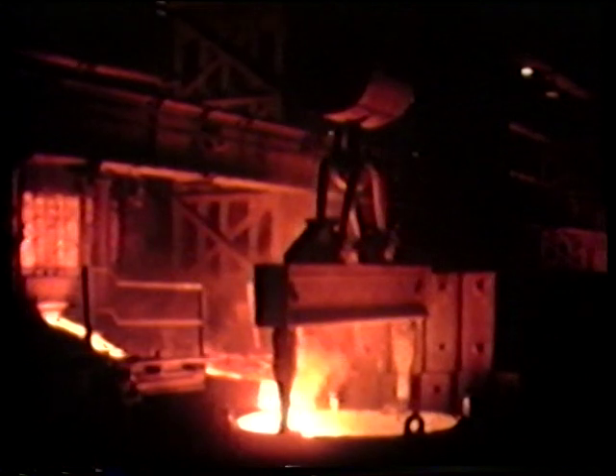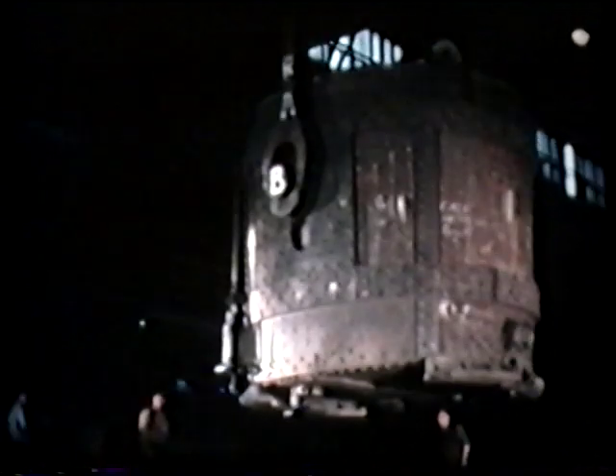Over 200 tons of steel is required for the initial supply. It comes from 3 acid open hearth furnaces tapped simultaneously into the ladles. This synchronization requires coordination of the highest order, from the charging of the furnaces to the pouring of the steel into the mould.